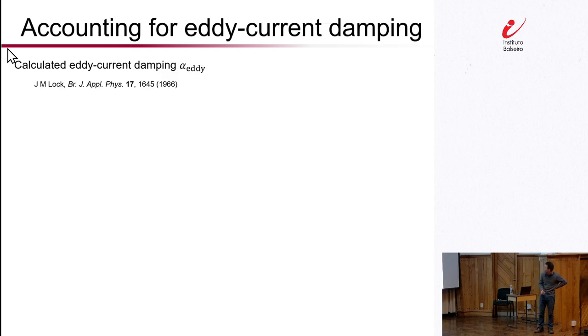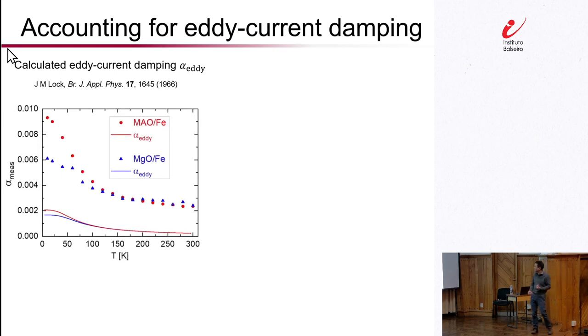Okay, so just looking at this, it seems conceivable that eddy current damping could account for the fact that we are getting higher damping from less scattering. But let's look at it even further. It turns out there is a nice model established in the 1960s allowing us to calculate the actual eddy current damping parameter from the experimentally measured conductivity. This is what we get, the solid curves down here. So again, you can see that the eddy current damping is not quite negligible, right? It's definitely there, accounting for maybe up to 10, 20% of the total damping, but it's not nearly enough to account for the entire temperature dependence.